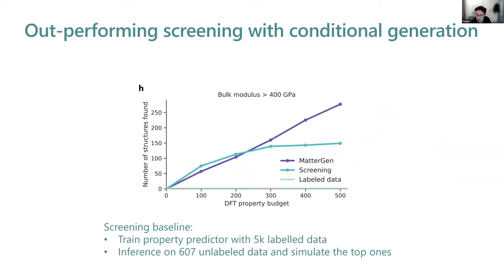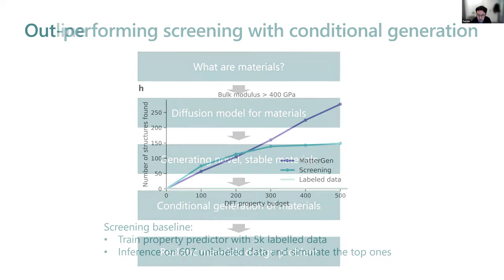So finally, I'm going to show one example where we really demonstrate that we outperform screening-based methods. Here, we are comparing with a screening-based baseline, and you can see that with an increased amount of DFT budget, our generative model keeps discovering novel materials with bulk modulus bigger than 400 gigapascal, while the screening baseline gradually saturates, because you are gradually exhausting the number of candidates that you have in your space. That's the end of the conditional generation part.